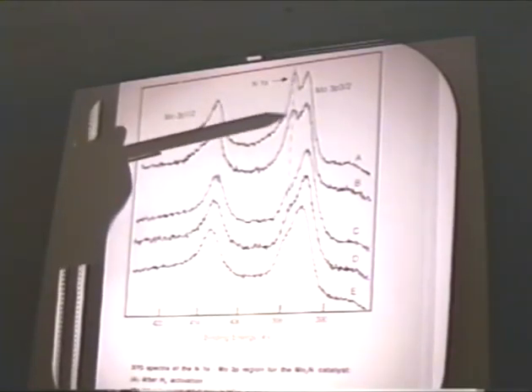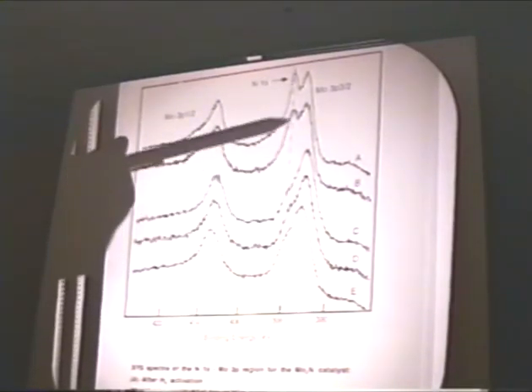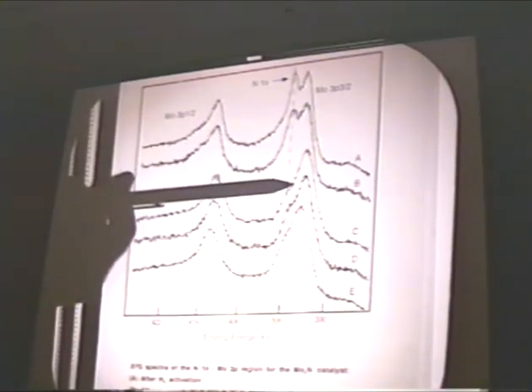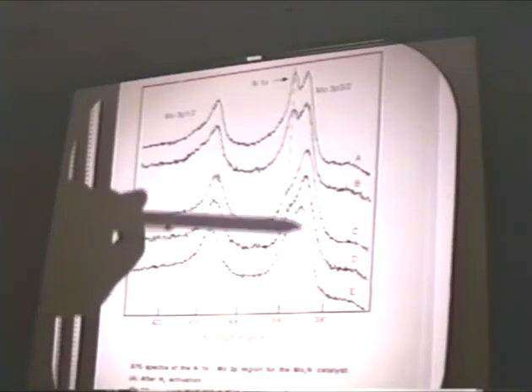The most striking feature here is the nitrogen 1s signal is diminishing. Even when we don't have sulfur compounds present, it is still weaker, although not as apparent as it is here, but especially when we have the sulfur compounds present, the nitrogen signal has really diminished significantly.